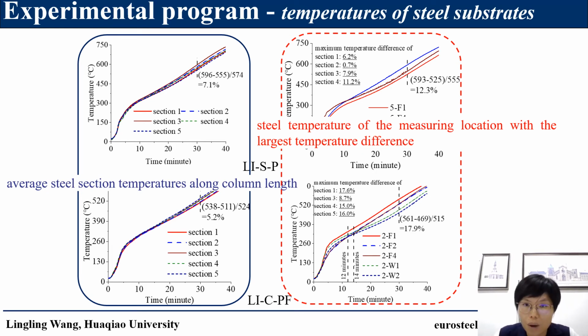Temperature differences seem to have developed very early during the fire test, and the same trends seem to have been maintained throughout the entire fire test. There is no evidence of the expected temperature drop. This suggests that extensive cracking and debonding, instead of detachment, would have been the cause of such large temperature differences. Furthermore, cracking and debonding occurred during the expansion of the loaded column before any sign of failure.